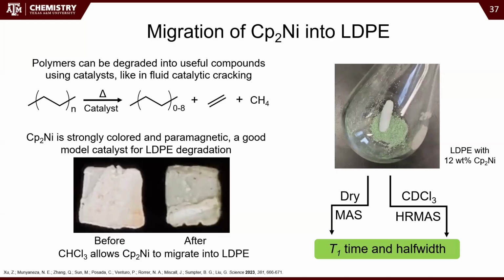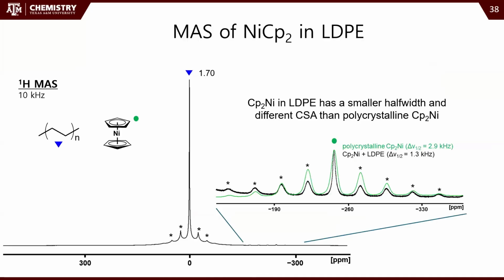So we can get that pretty easily. So we soaked that in. We found that we can get in about 12% of nickelocene, which is pretty good. And then we just rinsed that off really quick and took that material, dried it, and took that for NMR. And then we also re-wetted it and took that for NMR.